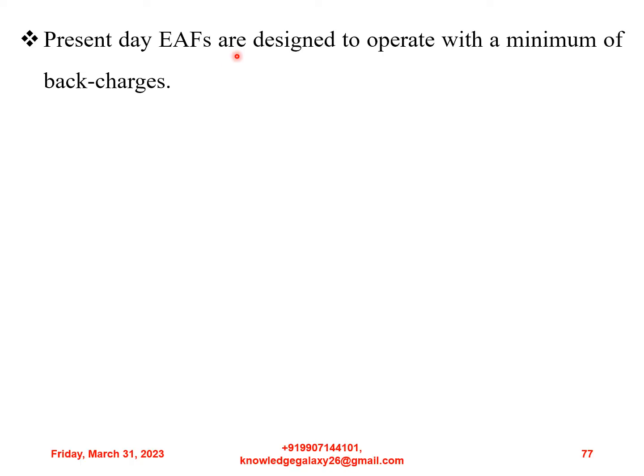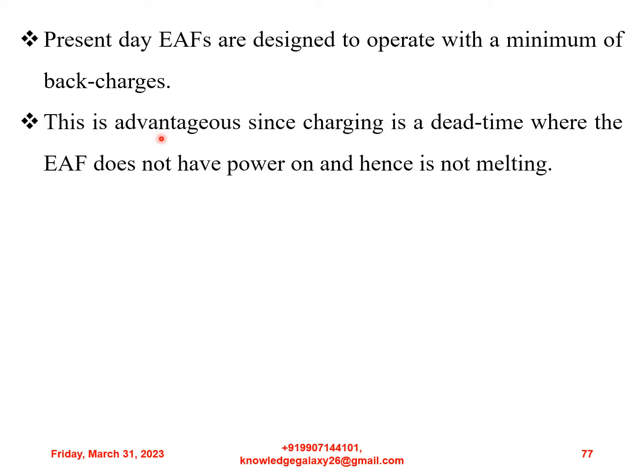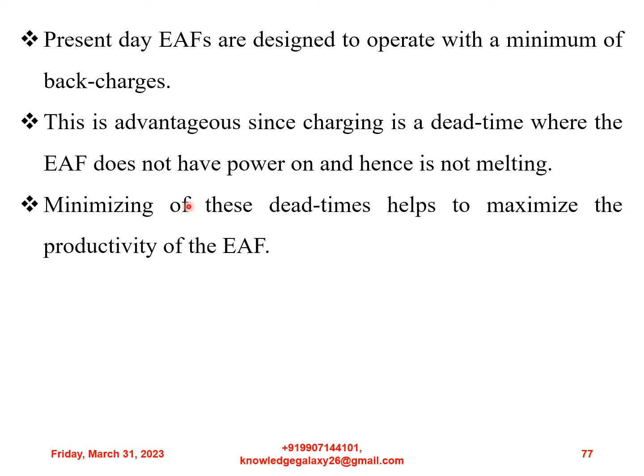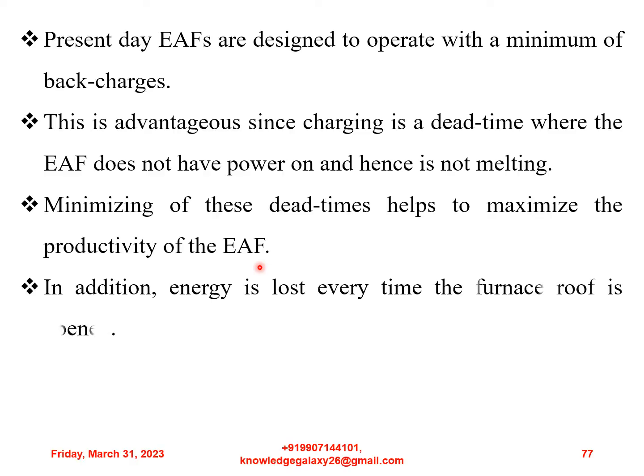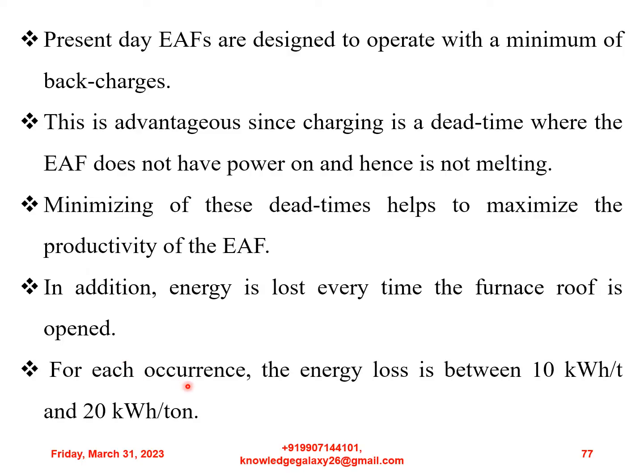Present-day electric arc furnaces are designed to operate with a minimum of back charges. This is advantageous since charging is a dead time where the electric arc furnace does not have power on and hence is not melting. Minimizing of these dead times helps to maximize the productivity of the electric arc furnace. In addition, energy is lost every time the furnace roof is opened. For each occurrence, the energy loss is between 10 kWh per ton to 20 kWh per ton.